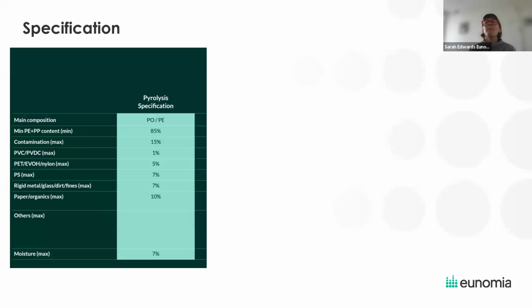Effectively we were looking at a bale specification of a minimum mix of polyolefin, PE and PP, of 85% and a maximum contamination level of 15%. The precise composition of that contamination was reflected in the main contaminants that I just highlighted. Contamination for PVC was capped in most cases around 1%. There was variation, but that's the general guideline that we came to within reviewing the work. PET, EVOH, and nylon had a maximum of 5%. Polystyrene 7%, and the metals and rigids around 7% as well, and 10% of organics, with moisture content aiming to be around 7% or less.